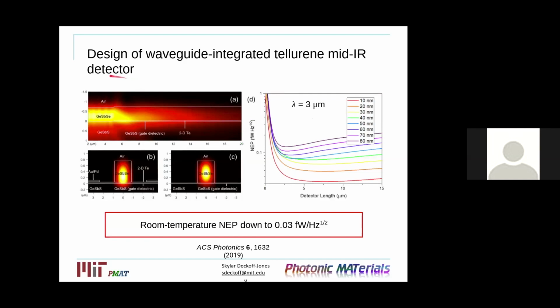So on the left, we do simulations to show that the tellurene, because of its high optical absorption, can very strongly absorb the optical mode, giving it a very high quantum efficiency. Additionally, because it's so thin, or we have the ability to control it to be quite thin, we see very little scattering at the interface between the photodetector and the waveguide due to mode mismatch, giving us very high quantum efficiencies. We then look at the performance of our photodetector if we vary the thickness of the tellurene. We only go to 10 nanometers because below 10 nanometers, we start to see an increase in the band gap, and we want to keep our device as a mid-infrared photodetector. So we're looking at 3 micron wavelength incident light.